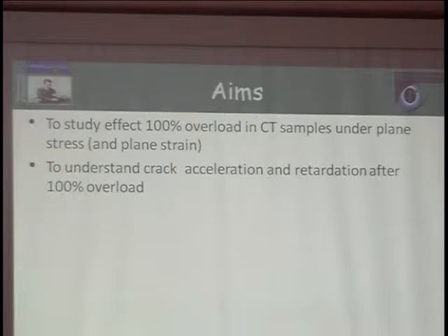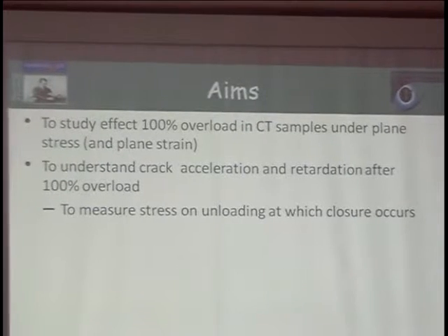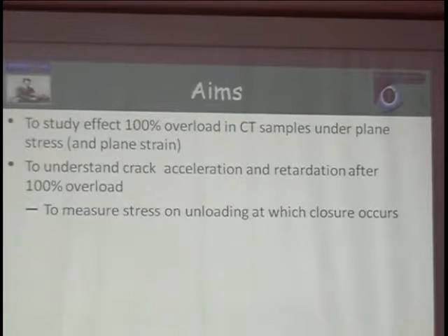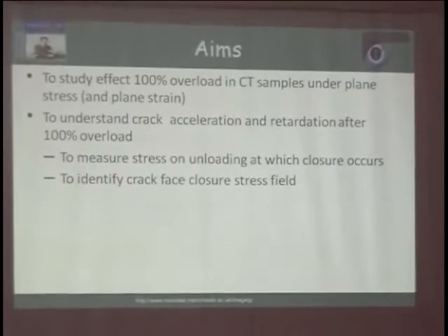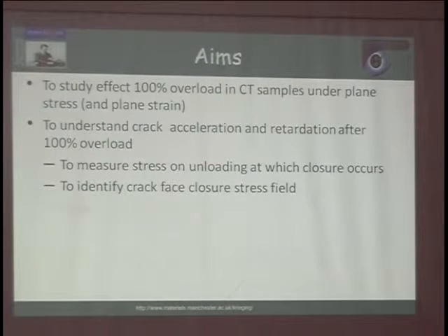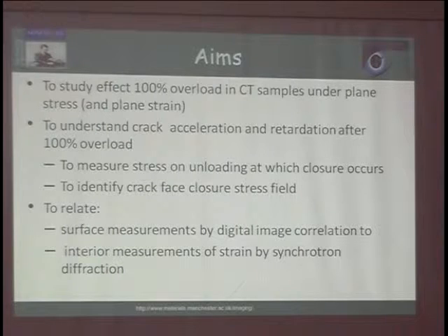As I say, we're going to look at 100% overload, so we're going to look at constant fatigue, 100% overload, and then fatigue thereon. And the idea was to try and use synchrotron diffraction to measure the stresses at the crack tip, to understand what's going on locally, and to identify what's going on in terms of plasticity-induced closure, and also to relate what goes on at the surface as measured by digital image correlation, and I know there'll be a number of talks looking at digital image correlation later, and also to compare that with what goes on in the interior by using synchrotron diffraction.